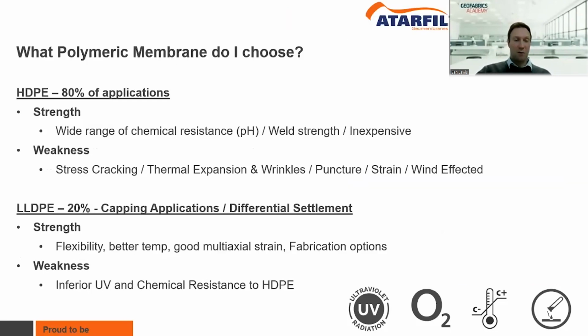So in terms of when you might select HDPE or LLDPE, 80% of applications would be HD, but with that you're getting a wide range of chemical resistance, weld strength, and it's pretty inexpensive. That's why people tend to go towards HD. But it does have stress cracking resistance issues depending on the grade, thermal expansion and wrinkle issues, puncture, strain, wind affected. It's quite light, obviously.